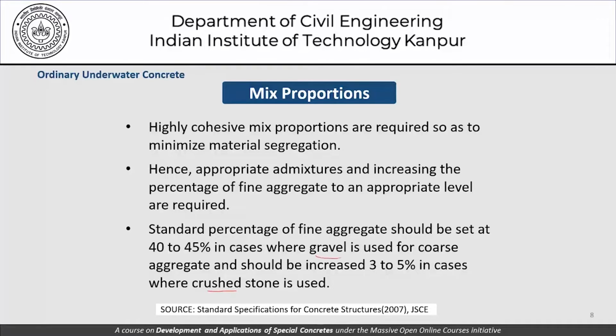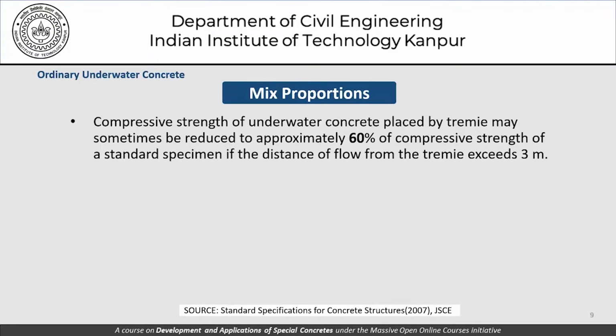Gravel here refers to round gravel, that is river gravel, and in case of crushed stone, a further increase of 3 to 5% is recommended over and above the 40 to 45% which is supposed to be used as a base. Compressive strength of underwater concrete placed by tremie may sometimes be reduced to approximately 60% of the compressive strength of a standard specimen if the distance of flow from the tremie exceeds 3 meters. An appropriate account of that has to be made.